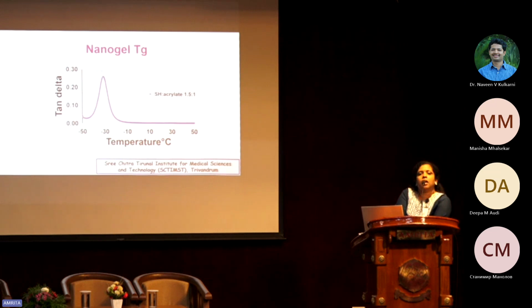So since we are introducing the nanogel as a plasticizer, we need to have a nanogel that is having low Tg, so low glass transition temperature, so that while incorporating it in the material, we can have a system with reduced Tg. So we have synthesized different nanogels based on this thiol-ene nanogel, or free radical solution polymerization based on tertiary butyl acrylate or PEG dimethacrylate or isobutyl acrylate or urethane dimethacrylate. And we have optimized this particular formulation because we got a very low Tg value for this particular nanogel, that's around minus 31 degrees Celsius.